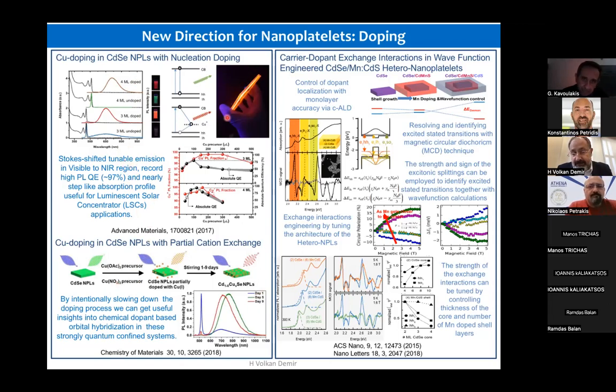And this is interesting, for example, for luminescent solar concentrators. So this is now a harvesting application, as opposed to the light emission applications I have thus far talked about. But with dopants, one can impart additional properties such as magnetic properties. And this is also something we are excited about, in particular manganese, because different from colloidal quantum dots, in this case we have monolayer precision. So we can choose these dopants to interact especially with a targeted part of the electron or hole wave function. And this type of high precision wave function engineering, we believe, is exciting to explore.